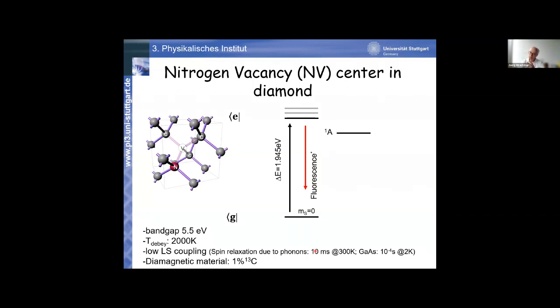But if you compare it with other solids like gallium arsenide, or I could also take silicon here, then typically these spin lattice relaxation times are more like microseconds at Kelvin temperatures. And if you go to higher temperatures, which sometimes for bioapplication, for example, is what you want to do, then these times would be reduced to picoseconds. But this is not so in diamond and silicon carbide, and this is why we like to work with them.